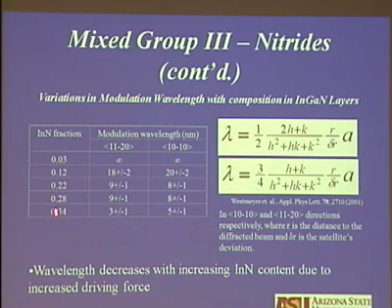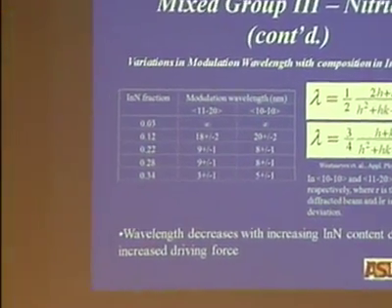As you increase the composition, the wavelength decreases as the indium content increases, and that's the formula we use to determine the wavelength. The reason is that the driving force for phase separation increases as you increase the indium content in your layer, and that's what is illustrated here.